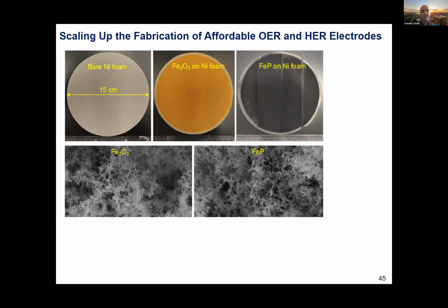The last part I would like to discuss is the scaling up of this technology for production of electrodes for electrolyzers. And we have investigated two approaches. One is to use a nickel foam, for example, or another substrate which is stable, and just use aerosol deposition with a baghouse filter to deposit on this foam, similar to what we have done with the bismuth oxide before. And then we have converted this from an oxide to a phosphide. So we have iron phosphide with a simple one-step process in a furnace.